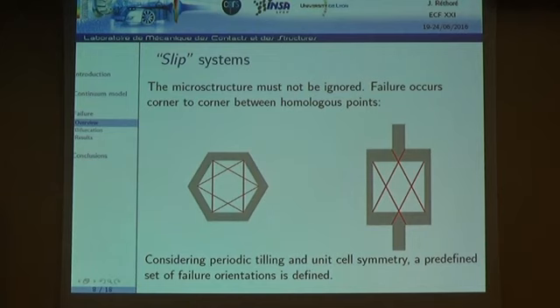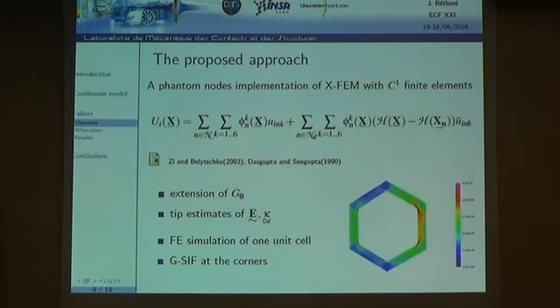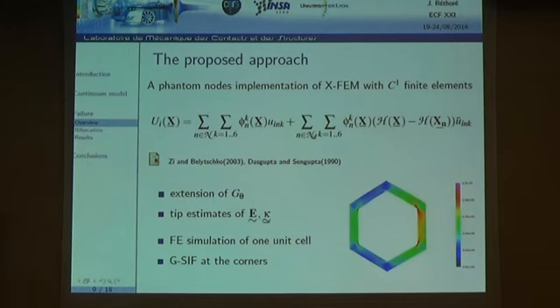For this particular structure you only have two possible crack angles. We developed a numerical algorithm to use this fracture criterion at the microscale, based on C1 continuous finite elements implementing gradient elasticity as the macroscopic continuum. For crack initiation and growth we use an extension of the G-theta method to compute the energy release rate for gradient elasticity.